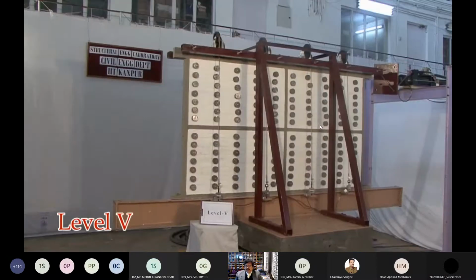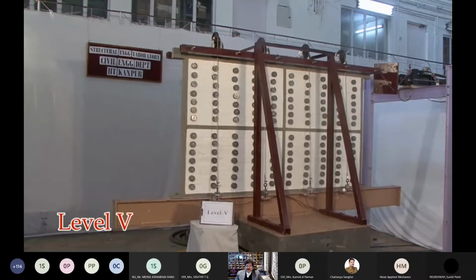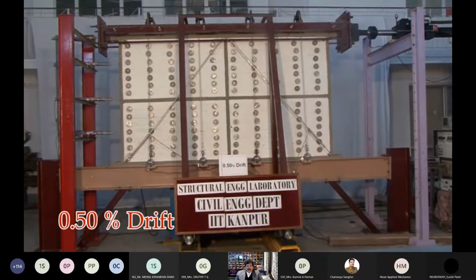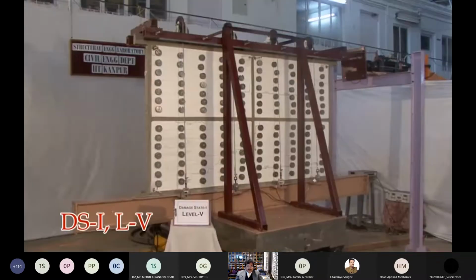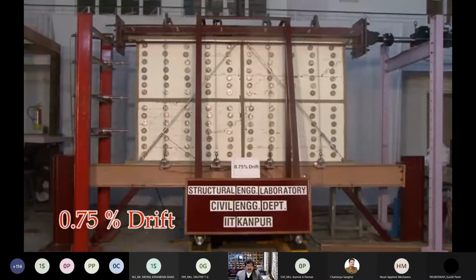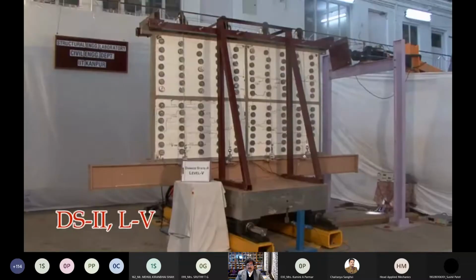Now you could see that it collapsed much earlier. But just by providing two elements, now you're dividing horizontally as well as vertically. Vertical is more important because now the unsupported height is only half of that, meaning the H over T ratio has been reduced to half, something in the range of 15. And if you recall from our previous presentations, this would do much better. 0.5% drift, and then you can see the damages. And we are all applying this L5. L5 means the zone 5 level out-of-plane shaking.